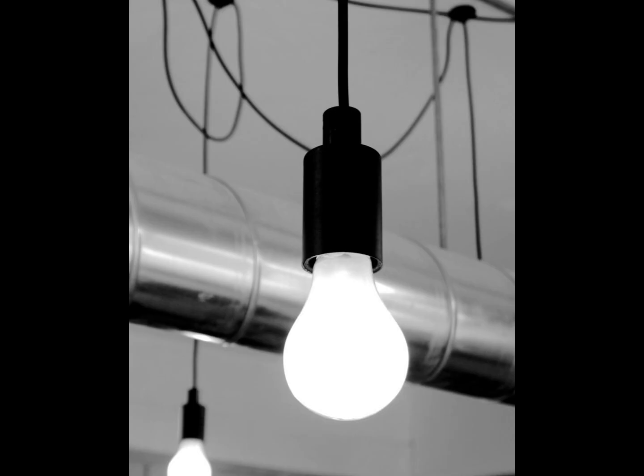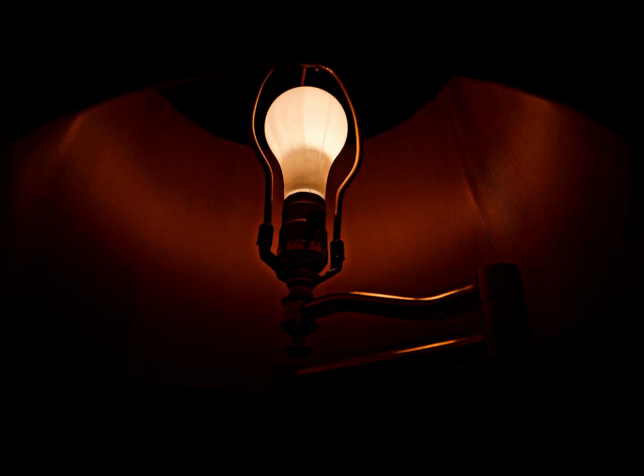Research work published in 2007 concluded that the story of the Goebel lamps in the 1850s is fictitious. The main difficulty with evacuating the lamps was moisture inside the bulb, which split when the lamp was lit, with resulting oxygen attacking the filament. In the 1880s, phosphoric anhydride was used in combination with expensive mercury vacuum pumps. However, about 1893, Italian inventor Arturo Malignani, 1865 to 1939, who lacked these pumps, discovered that phosphorus vapors did the job of chemically binding the remaining amounts of water and oxygen.